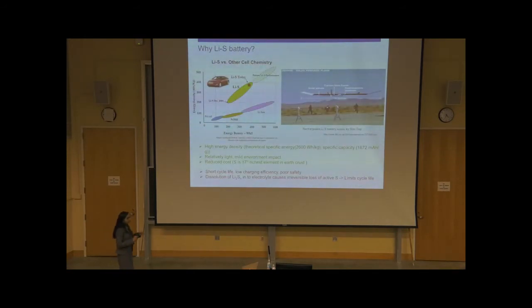The next type of system I want to talk about is deposition dissolution, where we can replace this intercalation with a high energy chemical reaction, and I'll focus on lithium sulfur batteries here. Lithium sulfur batteries are one of the most promising candidates to replace lithium-ion batteries in future because they can provide almost 5 times higher energy density compared to lithium-ion batteries. So they are somewhere in the range of 500 watt hour per kg compared to lithium-ion batteries, which are still in 100 to 200 watt hour per kg.